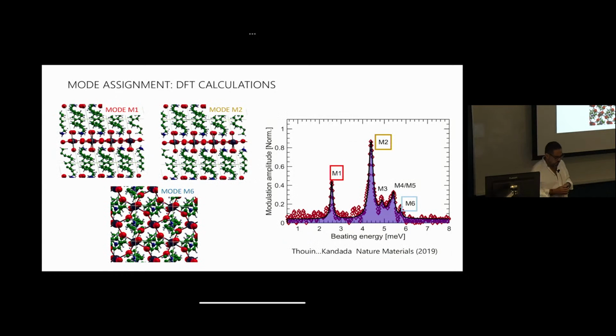You can do various means. You can either do a measurement where, if you had a very nice single crystal, you could do polarization measurements to really measure the Raman tensor, or you go to your friends and your colleagues and say, just with relatively standard nowadays ab initio methods, can you assign these modes? That's what these are. These come from just ab initio calculations of the system.